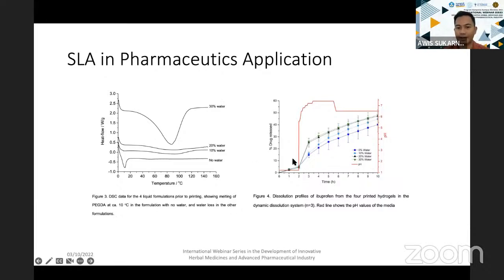And then here you can see the release profile for the 20 and 30% of water. The drug release is faster compared to the 10% and 0% of water. So it means the presence of water does improve the solubility of the drug in the formulation. But the 20 and 30% of water show a similar release profile. For the 10%, it's slightly slower, and for the 0% it's a lot slower compared to the rest of the formulations.